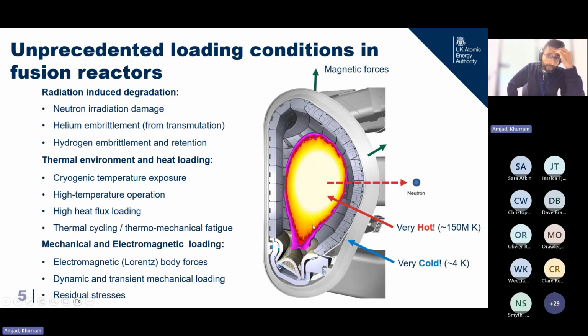Okay, if we come to the loading conditions that are experienced by components in this vacuum vessel, we have got quite a significant range. So let's first talk about radiation-induced degradation. As we do the fusion reaction, we generate very high energy neutrons, which are an order of magnitude higher than the energy spectrum of neutrons we typically witness in a fission reactor. So they cause significant damage and embrittlement.